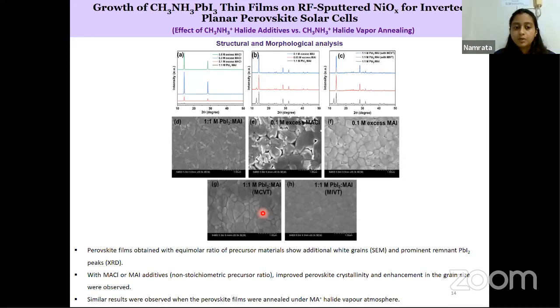Looking at the XRD and the SEM, we concluded that the perovskite films obtained with the equimolar ratio of precursor materials showed additional white grains and prominent remnant PbI2. With MACl or MAI additives in a non-stoichiometric precursor ratio, we saw improved crystallinity and enhancement in grain size. Similar results were observed when the perovskite films were annealed under an MA plus halide vapor atmosphere. So we see that the methyl ammonium chloride vapor atmosphere acts as a catalyst for enhanced perovskite crystallinity.